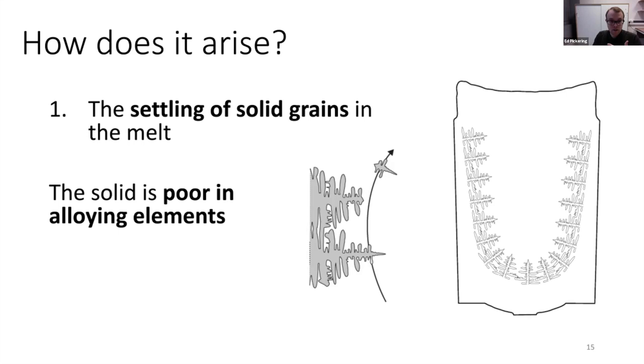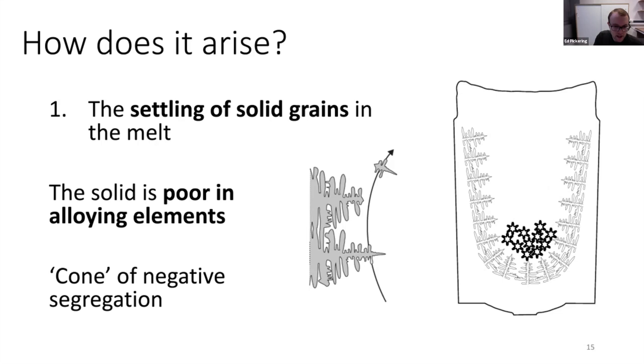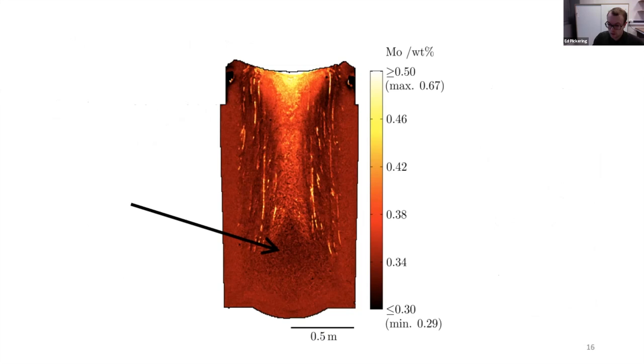And when they do that, they settle under the action of gravity. Just a reminder again, the solid is poor in alloying elements. Essentially, hopefully you can see this dodgy animation, all these crystals rain down to the bottom of the casting, remembering the solid is always poor in elements relative to the bulk. And that gives us a cone of segregation at the bottom of the ingot. We get a cone of negative segregation, and that is what this is at the bottom of an ingot. These are essentially all the crystals that have rained down towards the bottom of the ingot during solidification.